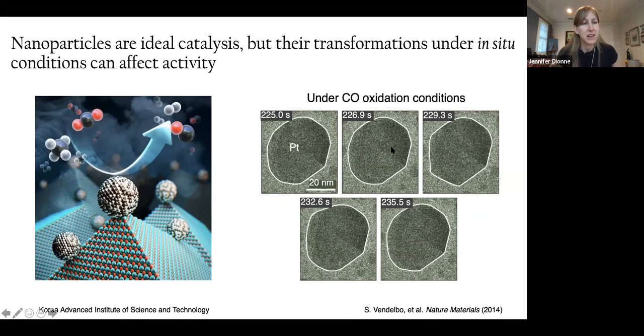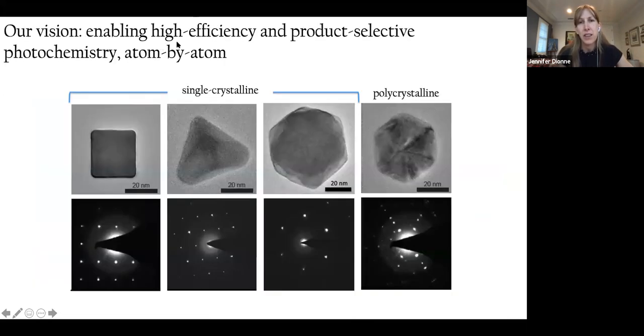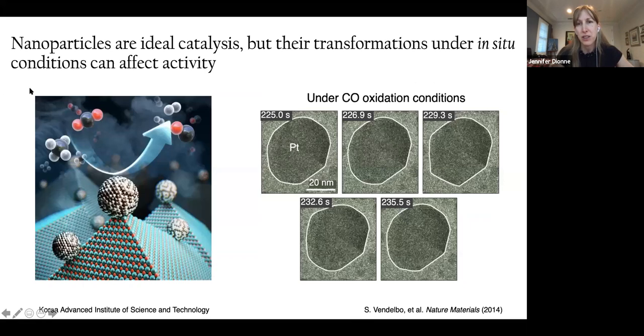But of course, when they are operating in a dynamic, reactive, gaseous, or liquid environment, they're going to be undergoing certain transformations. So here, for example, is a paper from Nature Materials published just about 6 or 7 years ago, where you can see that this platinum catalyst is rearranging under oxidation conditions. So we know that catalysts are changing their shape, and of course, that's going to change the number of active sites they have, since usually it's the sharp tips or the low coordinated sites that are the most active.